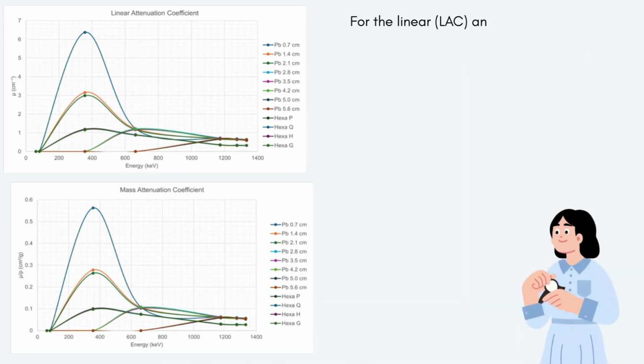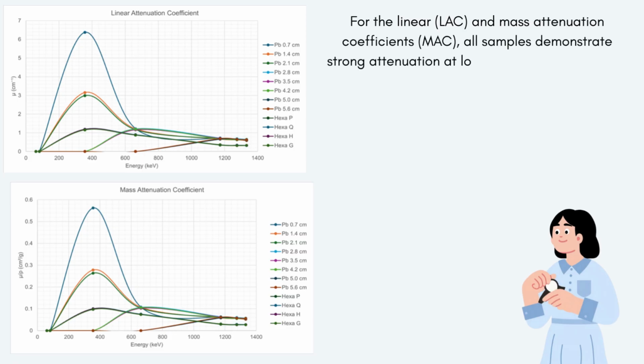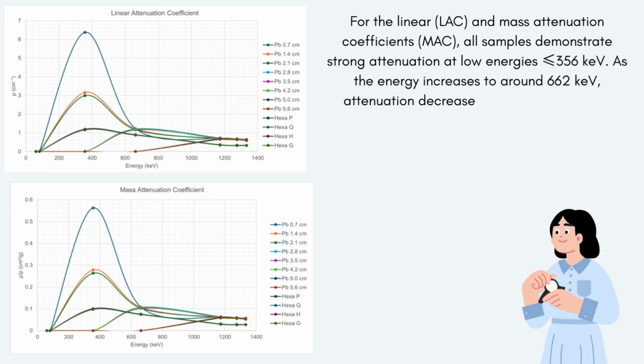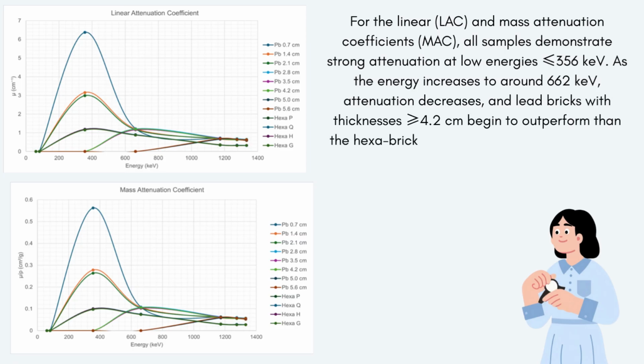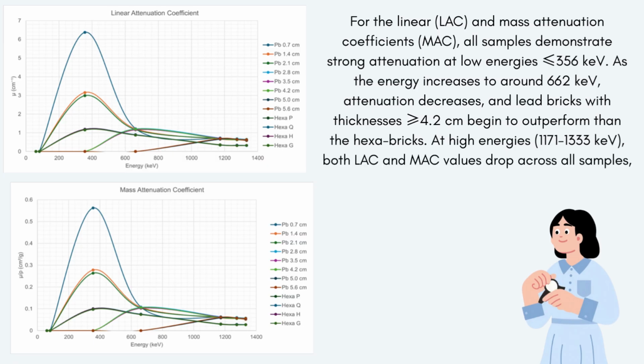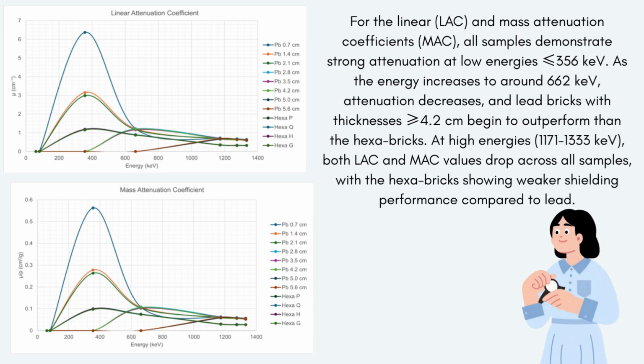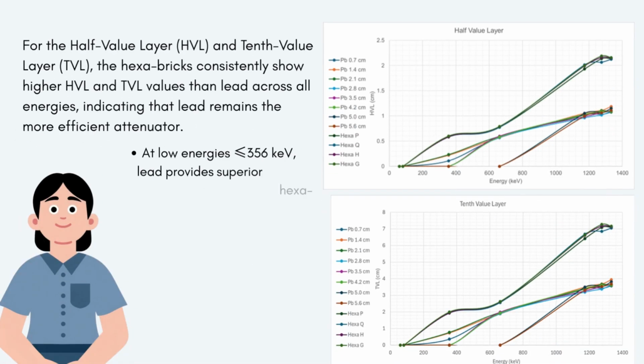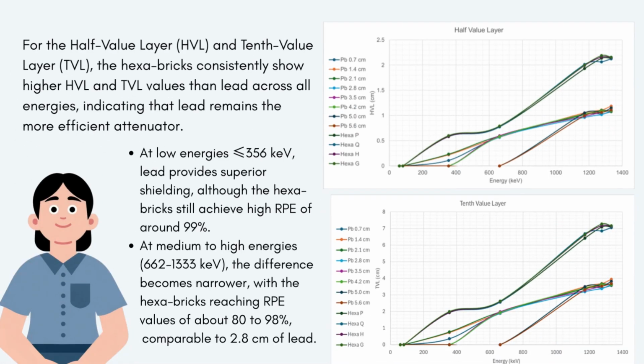For both linear and mass attenuation coefficient, all samples show strong attenuation at low energies. As energy rises to about 662 keV, attenuation drops and lead bricks thicker than 4.2 cm start to outperform the hexabricks. At high energies, linear and mass attenuation coefficient fall for all samples, with the hexabricks providing weaker shielding than lead. While hexabricks show higher half and tenth value layer than lead, they still offer strong protection.